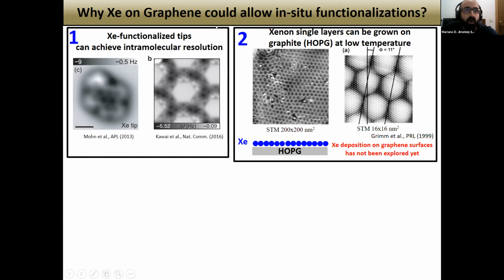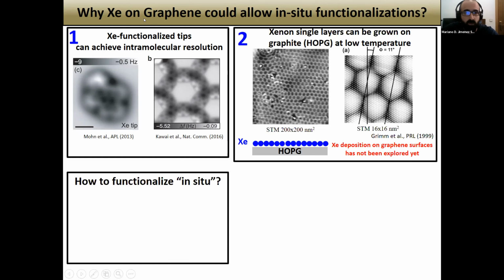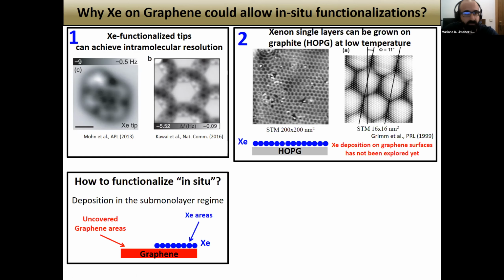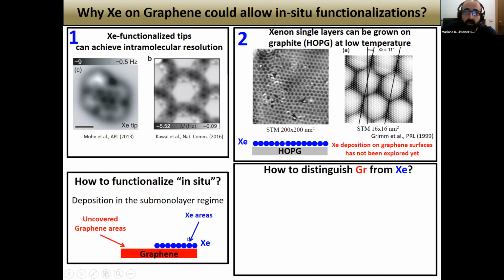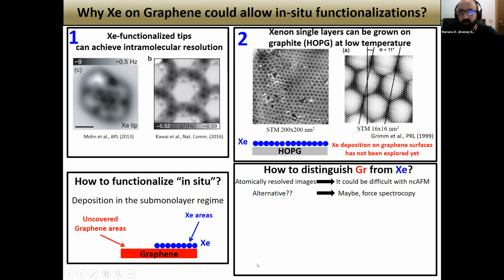And how do we employ this xenon on graphene to perform in situ functionalization? The idea is to deposit the xenon in the submonolayer regime and see if we can obtain separated regions of uncovered graphene and xenon areas where the tips could be functionalized. And how do we distinguish graphene from these xenon areas? The first idea is to use atomically resolved images. Nevertheless, it could be difficult to do with AFM because of the low reactivity of those species. Is there any alternative? Maybe force spectroscopy could be. And how does this force spectroscopy work?